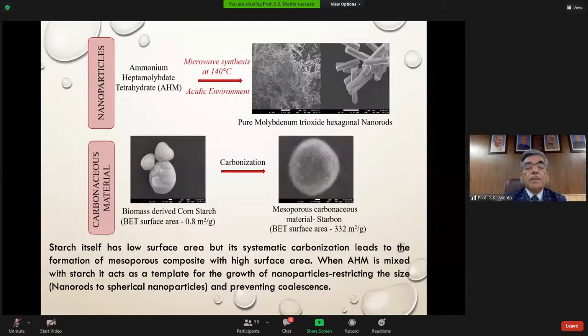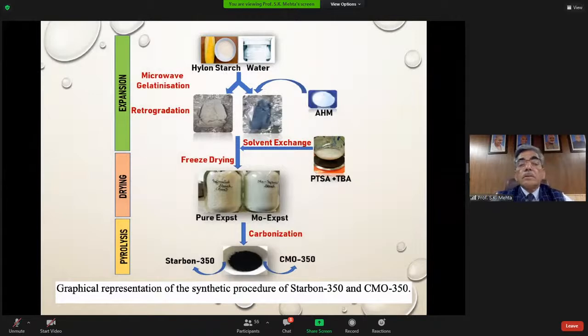When AHM, that is ammonium heptamolybdate tetrahydrate, is mixed with starch, it acts as a template for growth of nanoparticles, restricting the size, that is nanorods to spherical nanoparticles, and preventing any coalescence, because in nanotechnology, coalescence is a big issue. So we have to prevent that. So this is the overall sketch. Here, the starch was taken with water, and then microwave gelatinization was done, and retrogradation was done, and AHM was added. Then we have freeze drying, we have solvent exchange, and you get a pure molybdenum expanded product. And after carbonization, you get two forms, that is Starbon and CMO. So this is a graphical representation of how these two are formed.